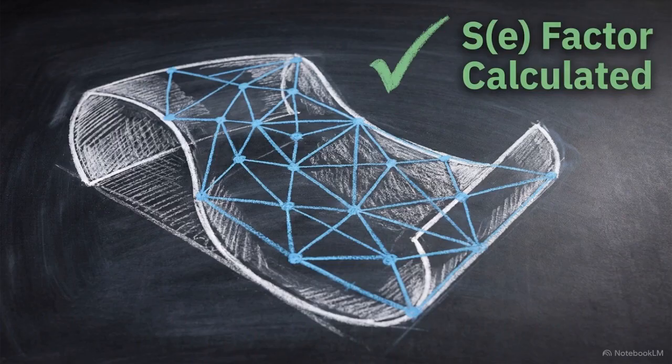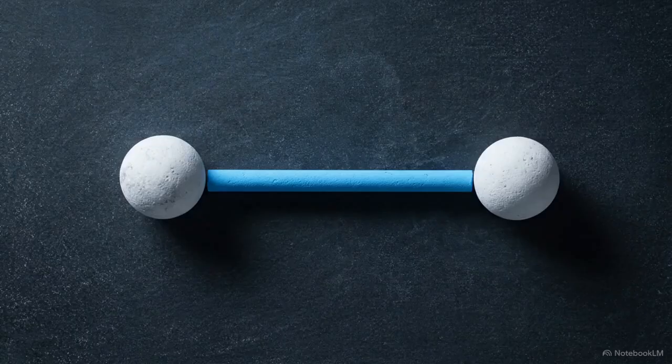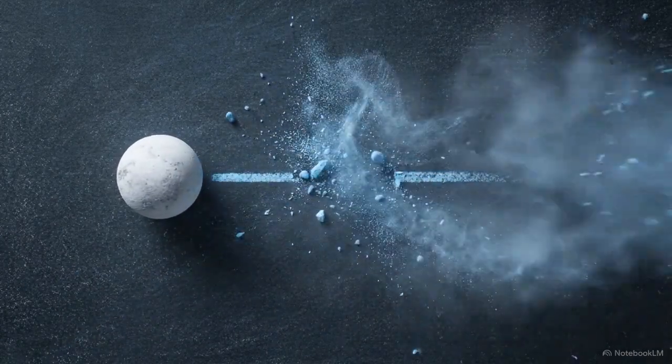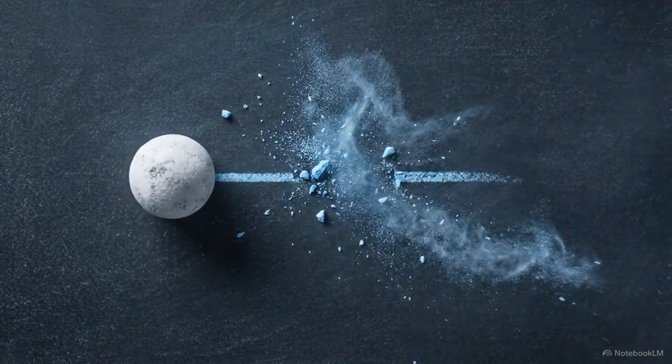Once the lattice is mapped as a graph, evaluating a material's plasticity becomes a purely geometric calculation. Consider a single bond deep within a fully coordinated cluster of the atomic network. To simulate a moving dislocation core, we virtually sever this specific connection, completely removing the edge from the graph. A breadth-first search algorithm then begins scanning outward from the severed nodes, searching for an alternative connection. The algorithm identifies the shortest possible alternative path that still links the two separated points.